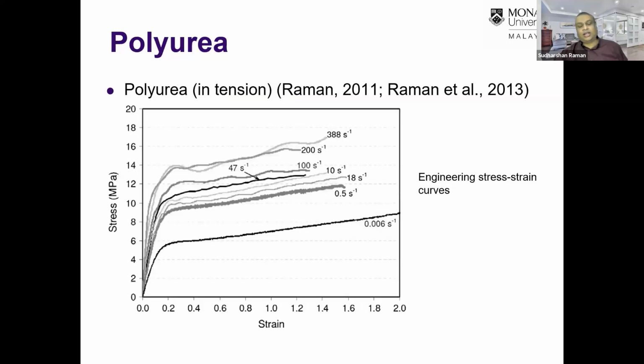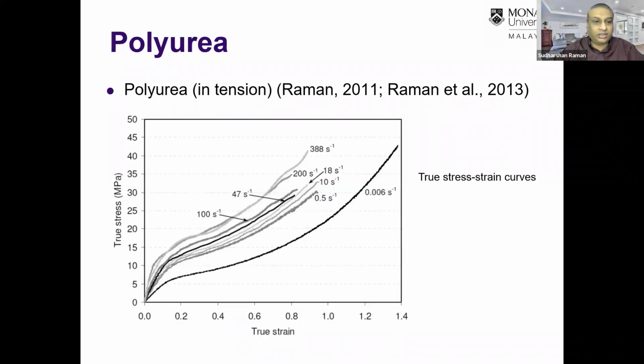And then when we tested it under different strain rates, at increasing strain rate up to close to 400, we noticed that the E value, the initial elastic properties of the material, actually stiffens when the strain rate is increased. This is the true stress strain curve of the polyurea that we tested, and it is available in a publication in Materials and Design from the year 2013.